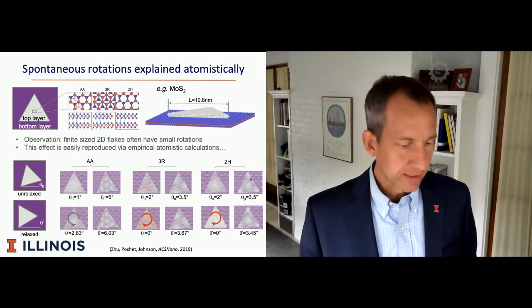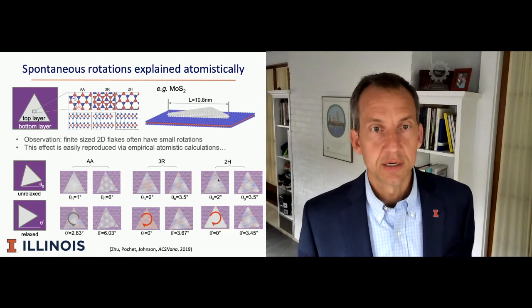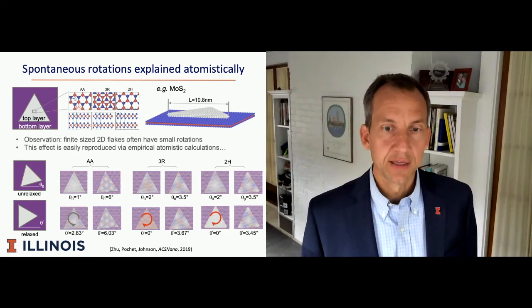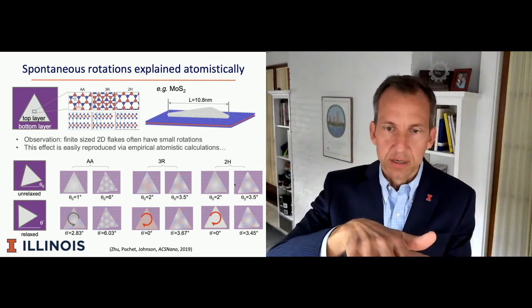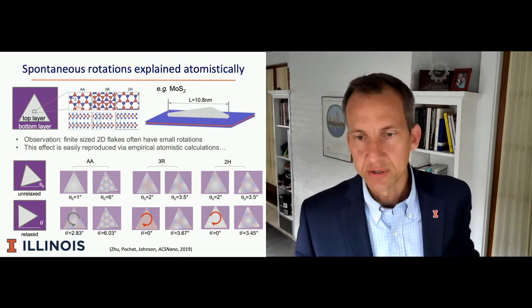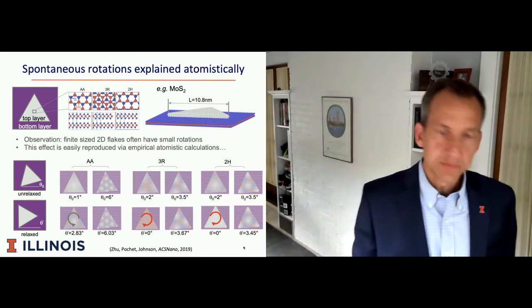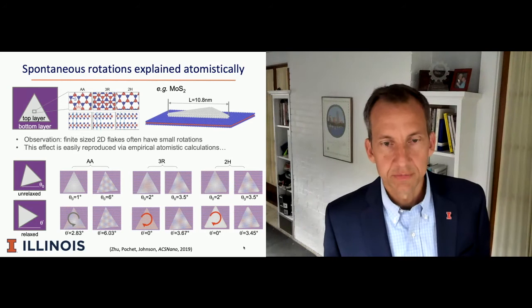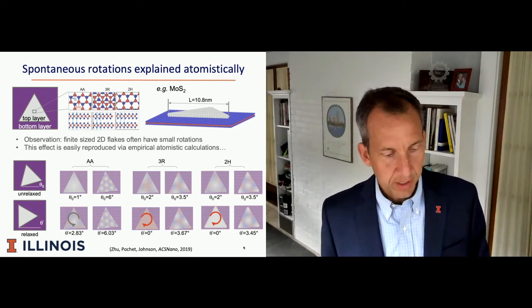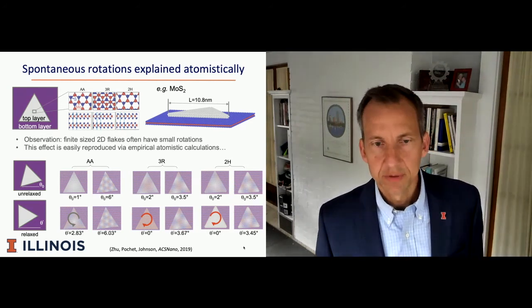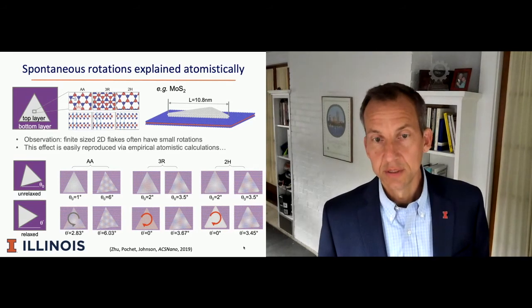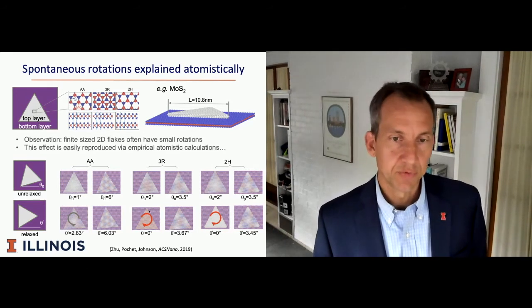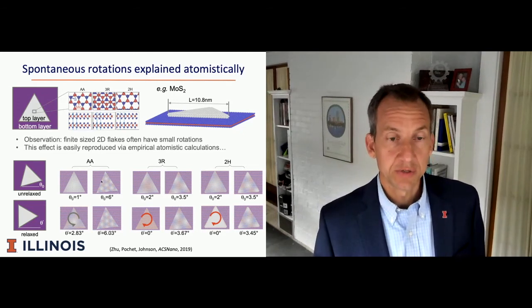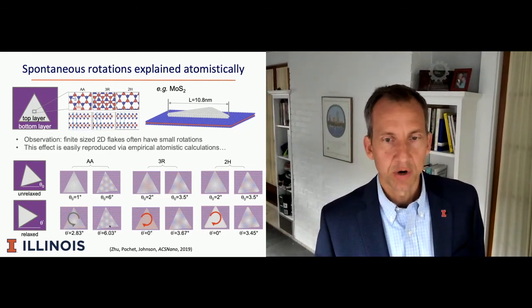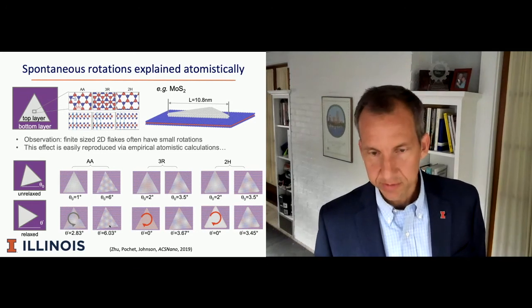Again, we can repeat the experiment for 2H stacking, which is structurally a lot more like AA stacking. Start at 2 degrees, and it does what 3R stacking does. It goes to the 0 degree rotation. We start at 3.5, it barely moves. So we can observe this phenomenon of spontaneous rotation of the flakes, and we suspect that there is some relationship to the moire pattern, because when we do the calculation, we can also see this moire showing up in the stacking of the atoms.